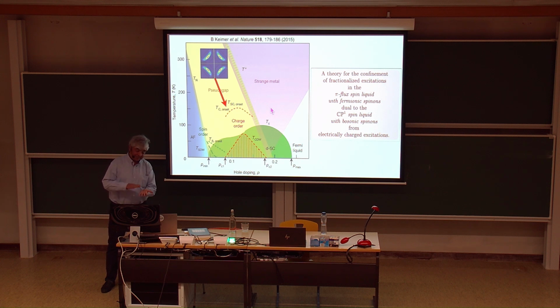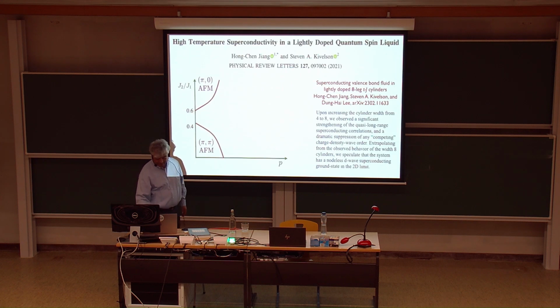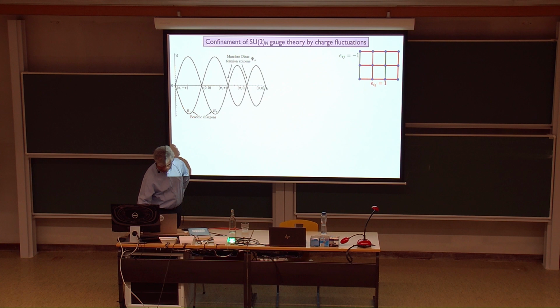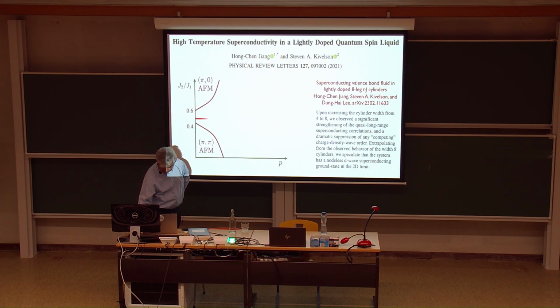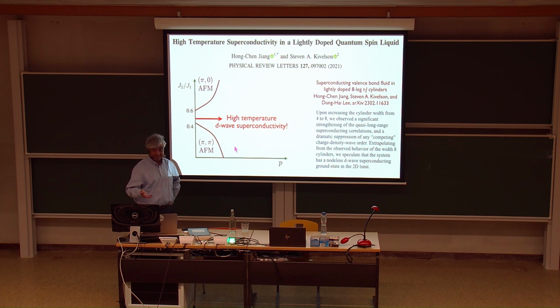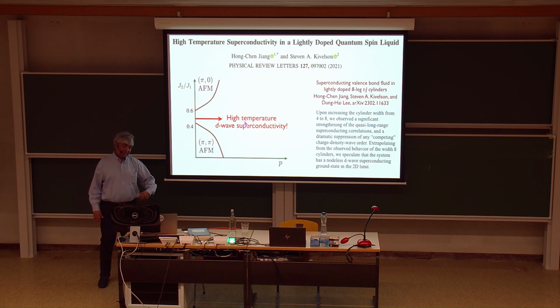If you take a square lattice and then maybe frustrate it a little bit, what came out of this study here is that the physical value of J2 in the cuprates is 0.1 or something. And when you do numerical studies at 0.1, down here, now there's starting to be evidence for D-wave superconductivity, but it's rather delicate. About 100 Kelvin is still a very low temperature on the scale of these theories. It's very delicate with charge density wave order. So when you actually start with a spin liquid rather than an antiferromagnet, it's really robust. So I would say there you go. If you could get a square lattice system where J2 is around half of J1, you'd be in business. You want second neighbor exchange to be a little bit larger. That's what I would say.